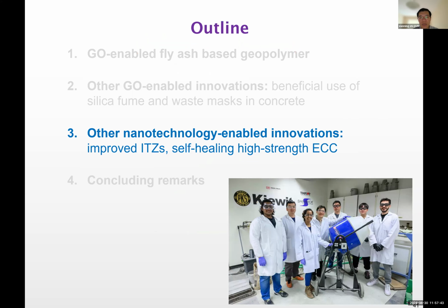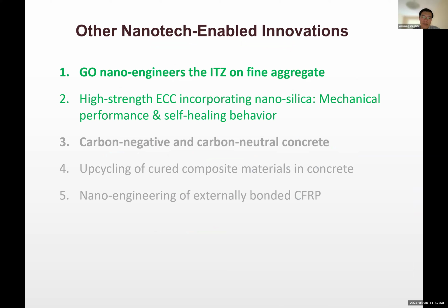So the last part is other nanotechnology enabled innovations. I'll talk about two examples. Again, there are so many examples, but I'll only focus on two. The first one is you can use graphene oxide to engineer the interfacial transition zone on the fine aggregate. More recently, we've even done it on the coarse aggregate. The way you do it is you treat the sand or rock with that dark ink, and then put it into concrete, and that works like magic. That's another patent we found.